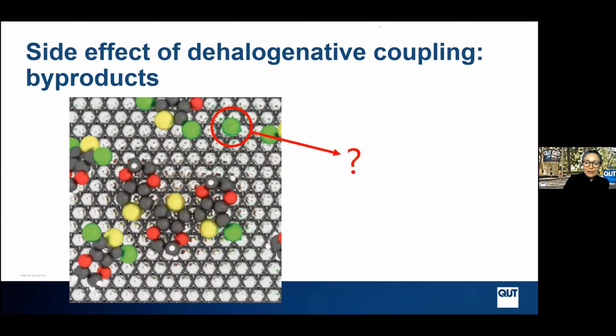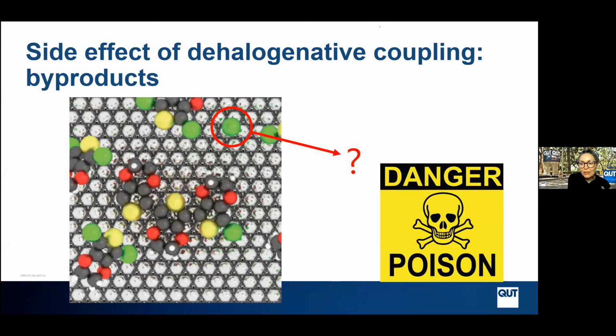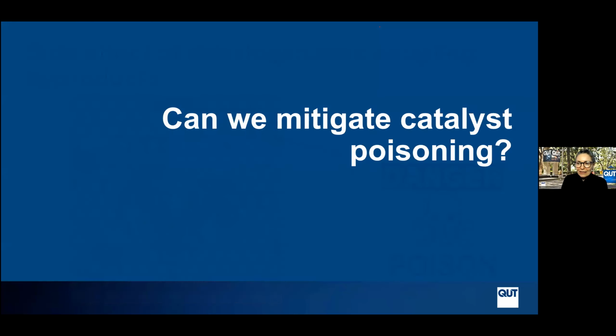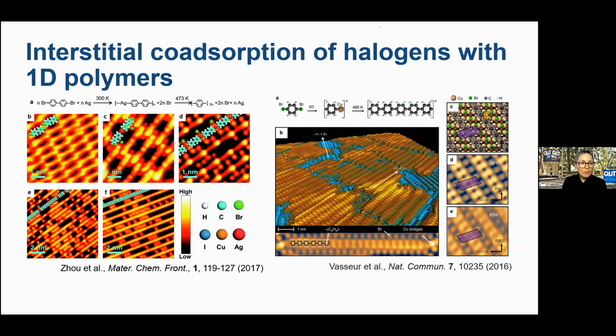But interestingly, one of the things that didn't bother us in this experiment was the byproducts. The removal of these halogen atoms tends to actually be fairly problematic in Ullmann dehalogenation reactions, and that's because they stick around and act as a poison to the catalyst. They're retained on the surface and they block the active sites on the surface. So one of the things we've also been interested in is whether we can mitigate this effect. We've done work to avoid it by working with other reactions, but if we're interested in doing Ullmann dehalogenation, this really seems to be unavoidable.